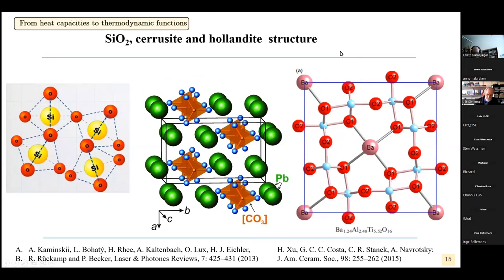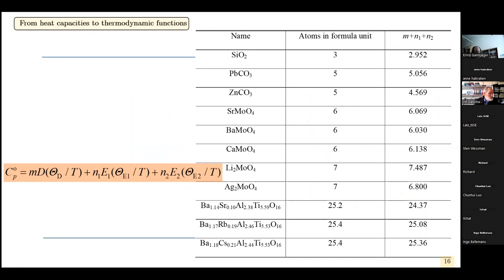For all these materials, we try to fit the data by the Levenberg-Marquardt algorithm. Here you can see the atoms in the formula unit. From theory, the sum of m plus n1 plus n2 — the pre-factors — has to equal the number of atoms in the formula unit. The Levenberg-Marquardt algorithm doesn't know about that, of course, but it approximates the theoretical value quite well in many cases. So it's an empiric approach but one that makes physical sense.